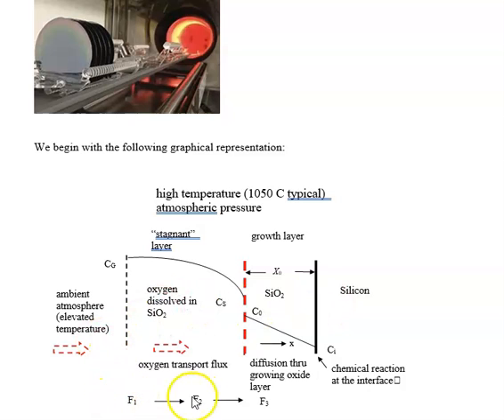Okay, so there's actually 3 different fluxes. Flux moving into the stagnant layer, and then the flux moving from the static layer into the growth layer, and then finally in the growth layer itself. All these fluxes must be equal, because if they're not, then we get pileups. So there's a continuous process flow from purely ambient, which is the highest concentration of oxygen, to the lowest concentration of oxygen at the diffusion layer, when the oxygen can no longer diffuse through the growing oxide layer, either because the temperature isn't high enough or the oxide layer is simply too thick. Then the growth process stops.